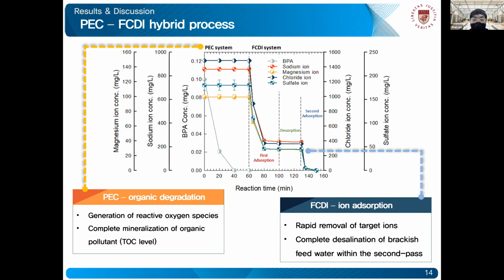As you can see from the figure in the middle, the PEC system shows the complete mineralization of an organic pollutant measured through a TOC level concentration. And TOC levels reached near zero after 40 minutes of operation. Also, no further oxidation byproducts were detected afterwards. Now, subsequently, the permeate of the PEC system was applied as the feed water for the FCDI system.